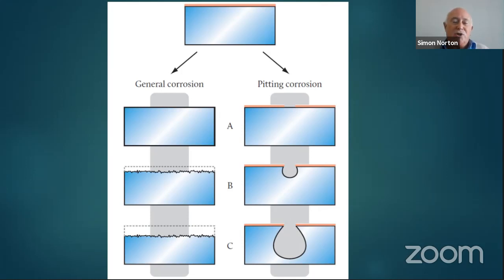But pitting corrosion, that's very dangerous. There you might get a break in the passive layer on stainless steel, and a pit forms. It looks very small at first, but little do you realize that the volume of the pit is enormous under the surface, and that can lead to catastrophic failure of your pipe or structure or whatever else you fabricated.